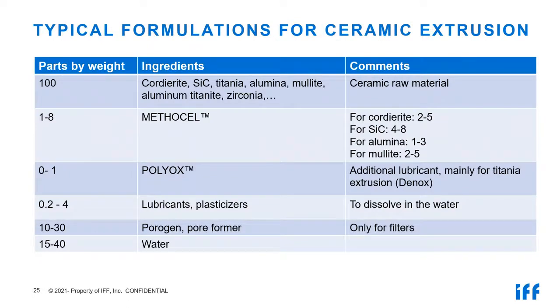At the end, I would like to give some typical formulations for ceramic extrusions. You might know it if you run extrusions every day, but if you start just with this topic, you might be happy to see some guidance. Normally you start with 100 parts of ceramic ingredients, whether it is cordierite, silicon carbide, titania, alumina, whatever. There are many options, and 1 to 8 parts of METHOCEL. Depending on the ceramic raw material, for instance alumina, you choose a lower content of METHOCEL, but if you choose, for instance, silicon carbide, you need a higher content, 4 to 8 parts per weight. In alumina, just 1 to 3.